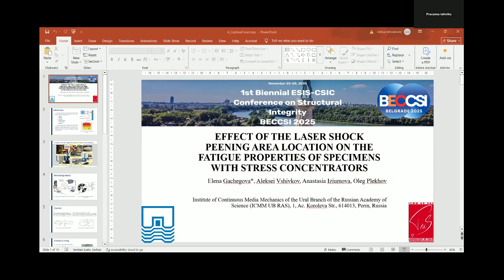And following this, similar tests were conducted on titanium alloy specimens made of titanium aluminum molybdenum. But here we use only one scheme, scheme number 2, because we know that this scheme was better than scheme number 1, and we had similar results as when we investigated the specimens from titanium grade 2.